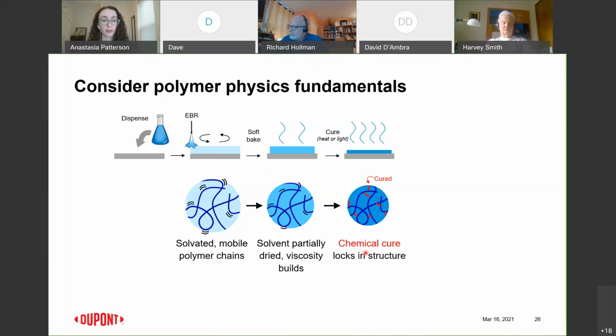And so we had assumed that this very extreme step was when that cracking was developing in the film, because it's the highest temperature change. It's the greatest chance for stress to be induced in the film. But when we asked, when does the cracking actually occur? Can we pull the wafer at each of these steps and take a look?